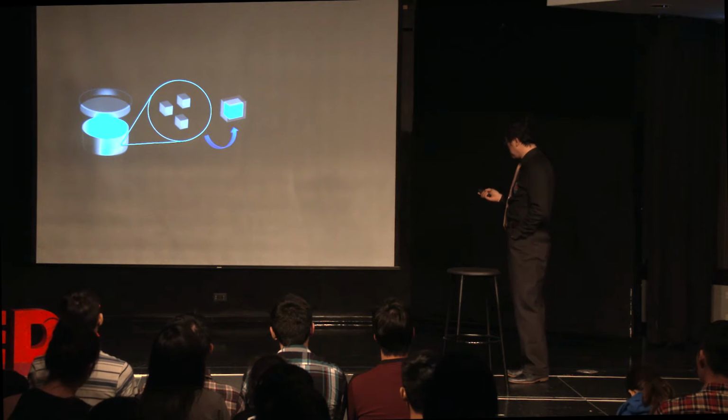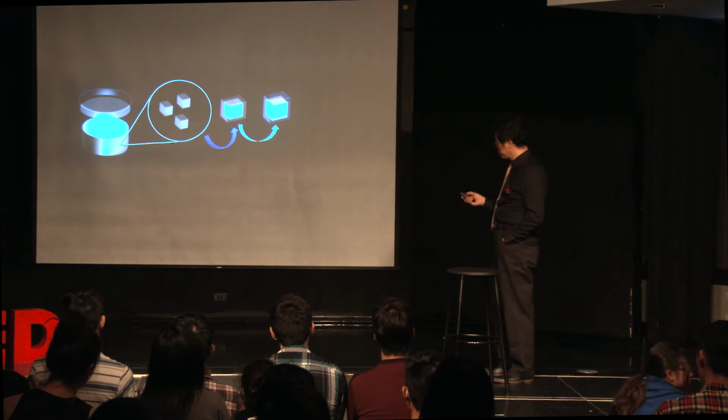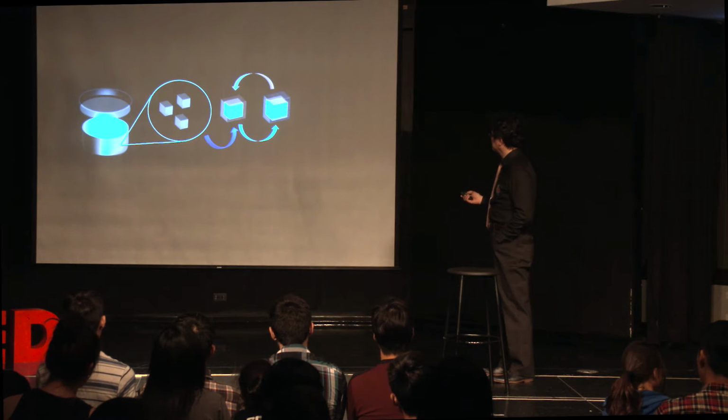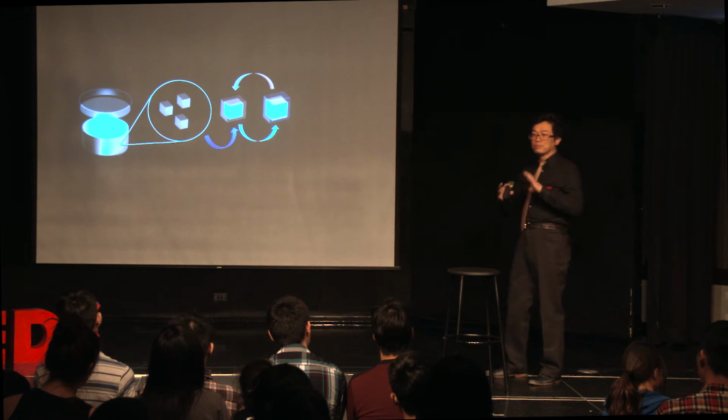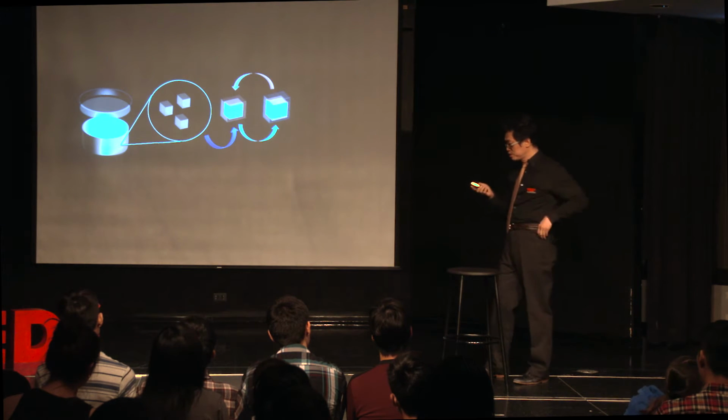Then the particle becomes another charge, for example, from positive to negative. So you give them another kind of positively charged polymers. So they will coat the surface again. And do this again and again and again. Now you form a layer-by-layer stitching of polymers on top of the crystals.